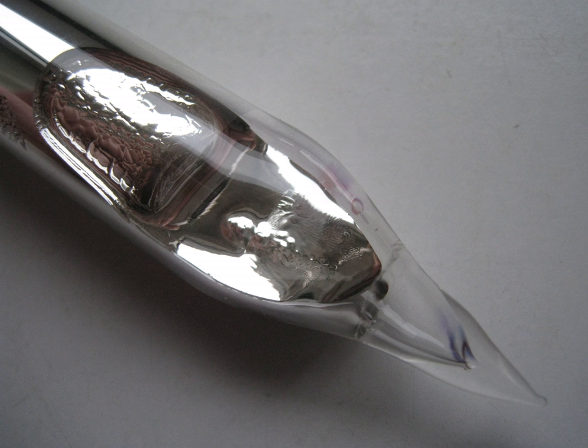They tried to generate elemental rubidium by electrolysis of molten rubidium chloride, but instead of a metal, they obtained a blue homogeneous substance which neither under the naked eye nor under the microscope showed the slightest trace of metallic substance. They presumed it was a subchloride. However, the product was probably a colloidal mixture of the metal and rubidium chloride.